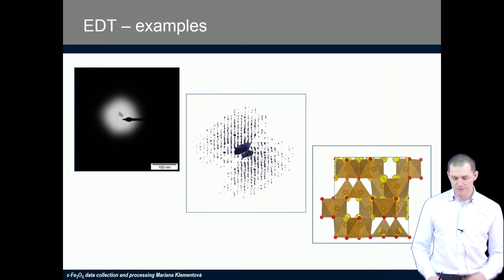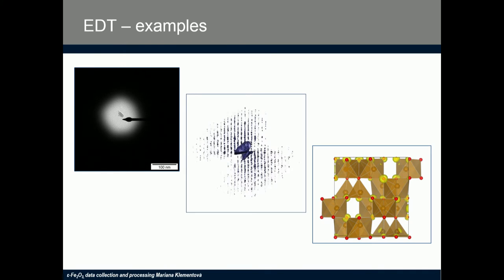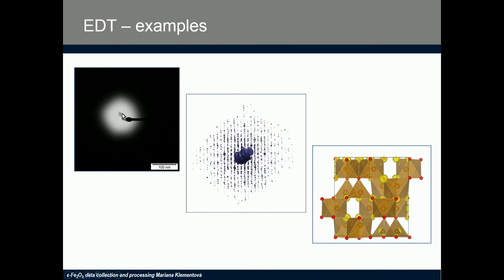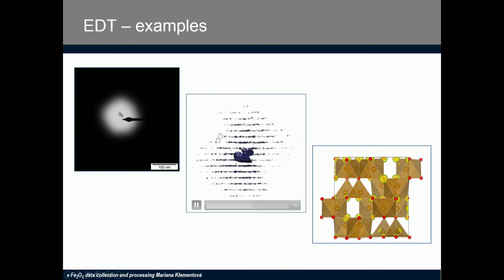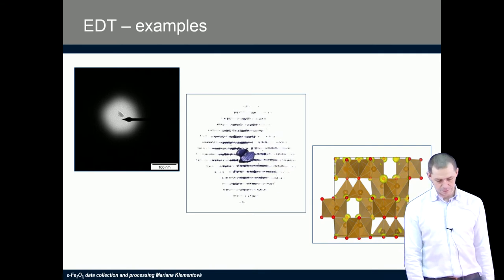And final example, just to show that we really can do things with very small crystals. This crystal here has dimensions of about 10 times 20 nanometers, and it allows a collection of a complete diffraction pattern like this, and then the structure solution comes out very nicely from it without any problem. So really the size is not a problem for electron diffraction.